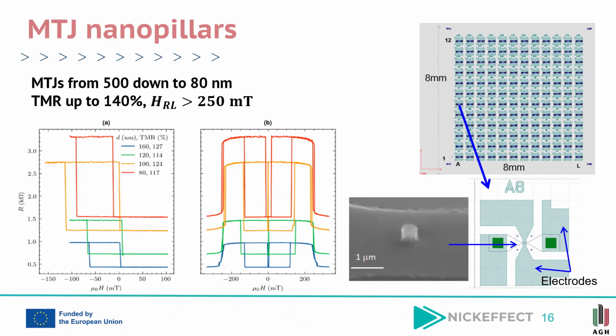The optical image shown on the upper right presents the layout of the fabricated MTJ device array on the wafer. A magnified view of a single device is shown below, illustrating the MTJ pillar located between the top and bottom electrodes. The graphs on the left present representative magnetoresistance loops measured for different MTJ pillar diameters. Clear switching between the parallel and antiparallel magnetic states is observed for all investigated device sizes, confirming reliable MTJ operation